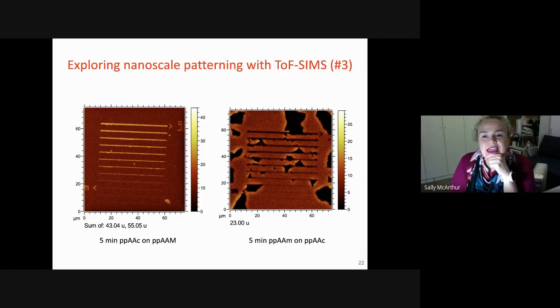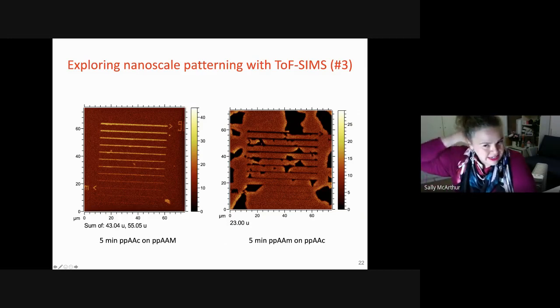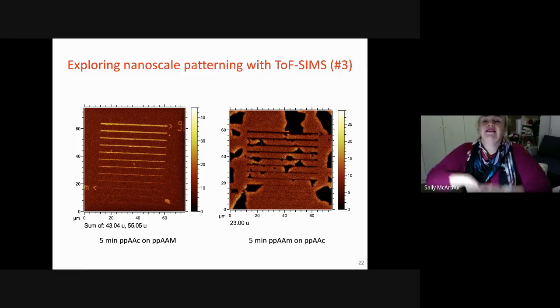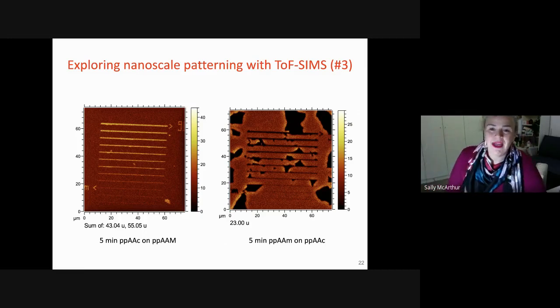And the interesting thing is that the order in which you pattern matters as well. So when we put the acrylic acid onto the allylamine, it works really nicely. If we reverse it and put allylamine onto acrylic acid, not so much. And so you can start to see here the acrylic acid film and the allylamine lines, the acrylic acid has actually lifted off the surface. And the allylamine has lifted off the surface as well here.